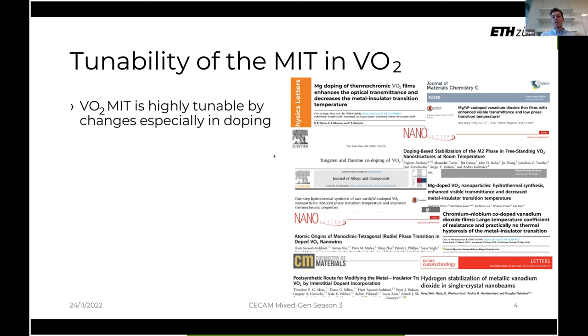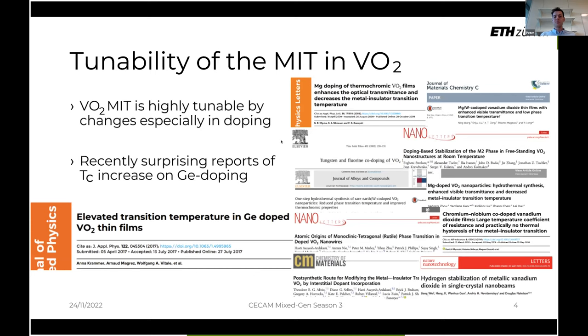And quite recently, an experimental group at EPFL, which is one of our collaborators, has found that under germanium doping, there is a marked increase in transition temperature in vanadium dioxide. This came as quite a surprise because very often it has been thought that only charged dopants are able to change the transition temperature in vanadium dioxide significantly. And indeed, germanium doping is not charged, where germanium has the same oxidation state, 4+, as vanadium in vanadium dioxide. So it came as a bit of a surprise that germanium doped VO2 thin films have a really high transition temperature, around 10 degrees higher than pure VO2. And so, in this research, we try to answer the question of how this happens, or whether we can shine light on this and explain what is going on.